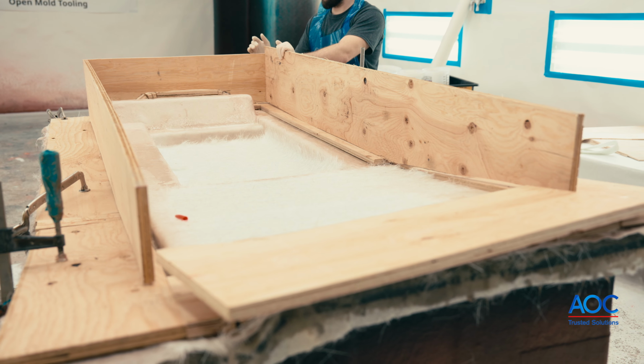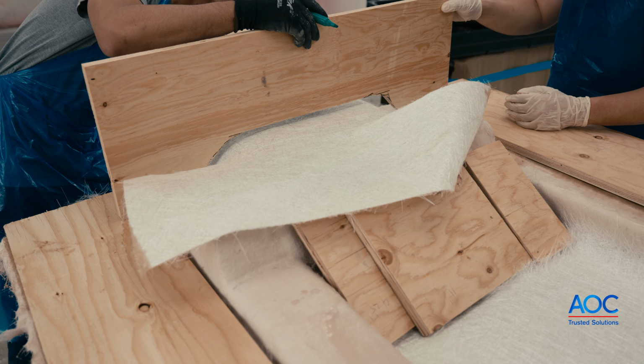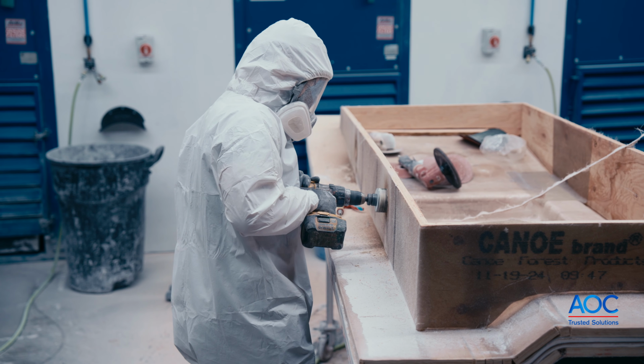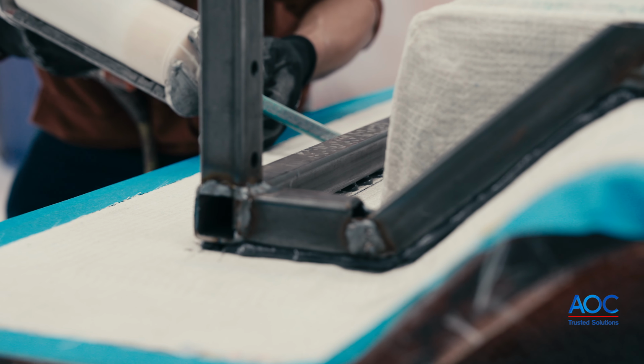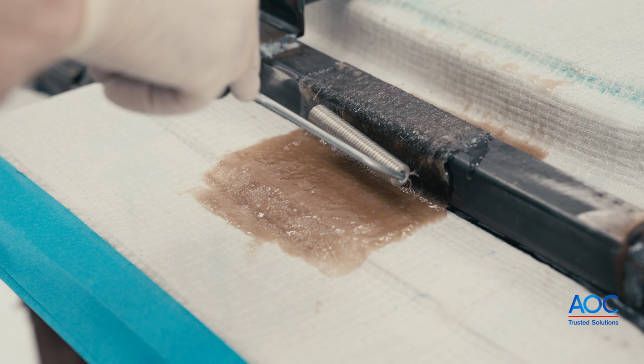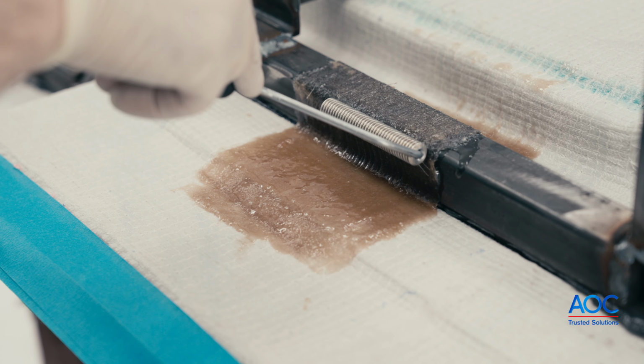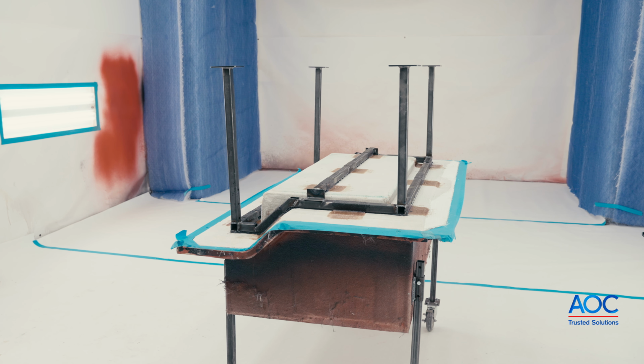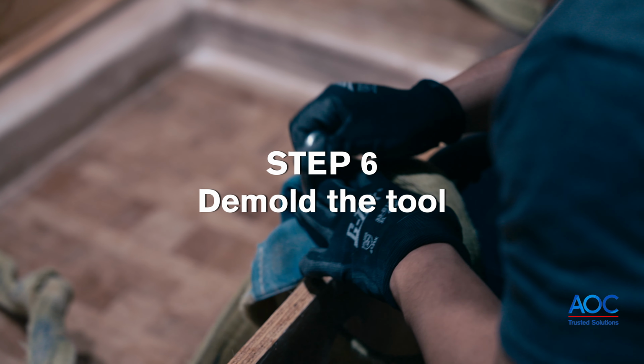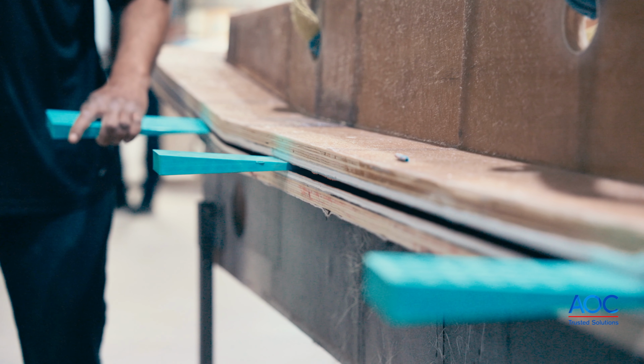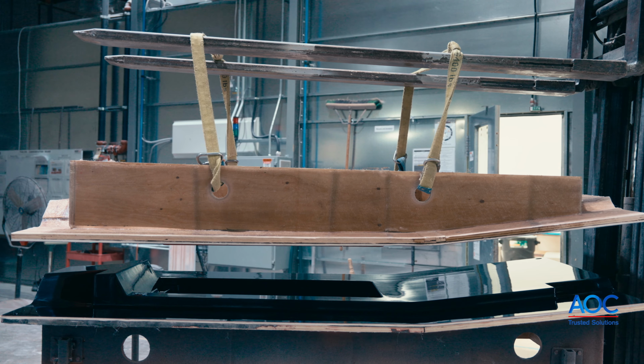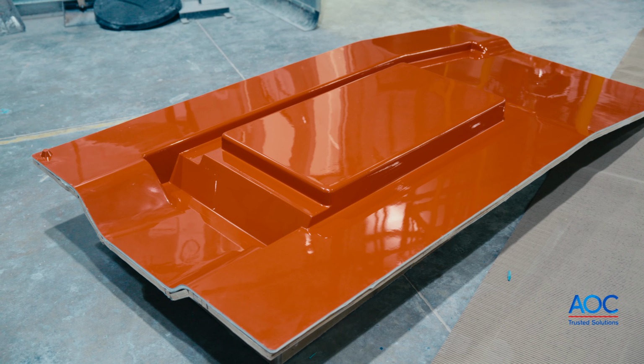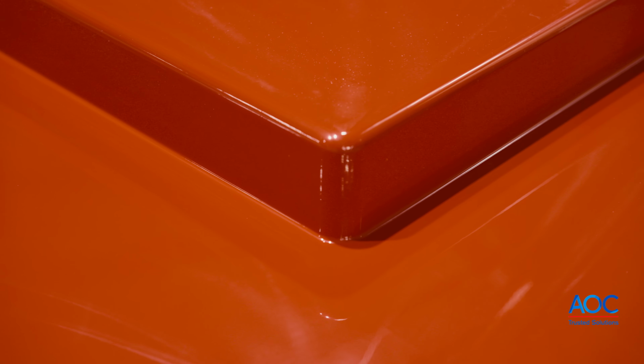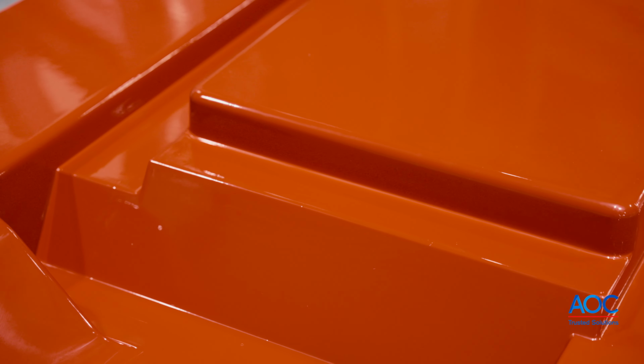The next step is to apply a frame to the back side of the tool. To reduce torsion during the demolding process, we recommend applying a solid frame around the tool. Secure the frame at multiple points using adhesive and laminate for stability. Finally, it's time to demold the tool. Using wedges, work around the perimeter and pull the tool off the master model. With the tool now demolded and inspected, your composite tool is ready for use or additional processing.